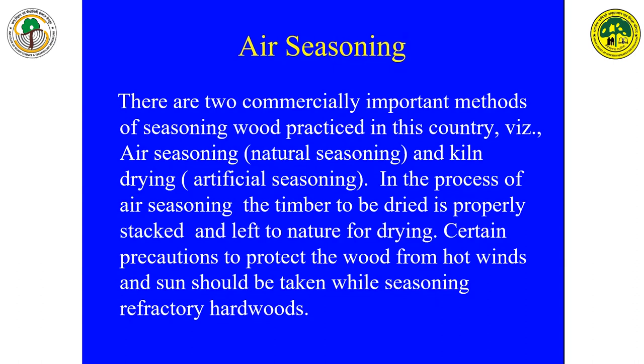So suppose you want to construct your house and you have time, then 6 months ahead you convert your logs into planks, ballis and scantlings and nicely stack them. I will show the photographs of how to stack them, and then leave them in nature. The place should be well protected from sunlight as well as rainwater, so that only air touches the stack, and gradually the stack loses moisture, and within 4 to 6 months, depending on the temperature and RH of that geographical region, our wood dries nicely to a very good level.